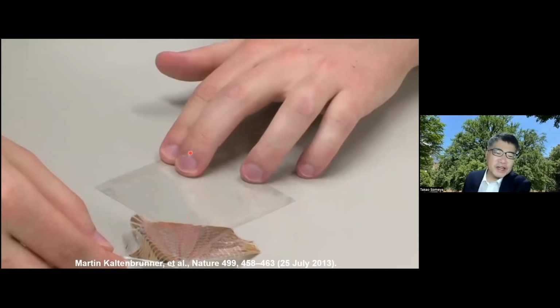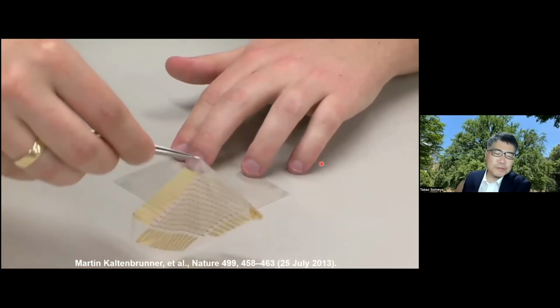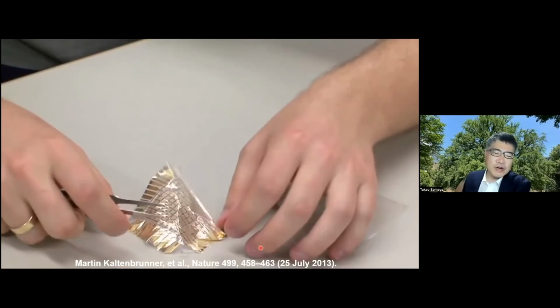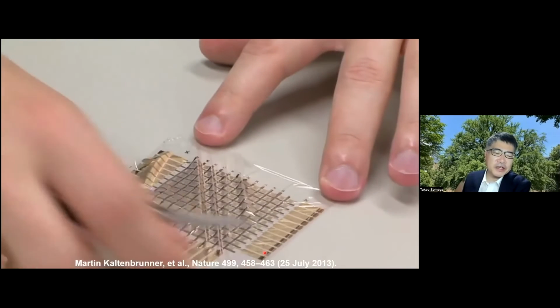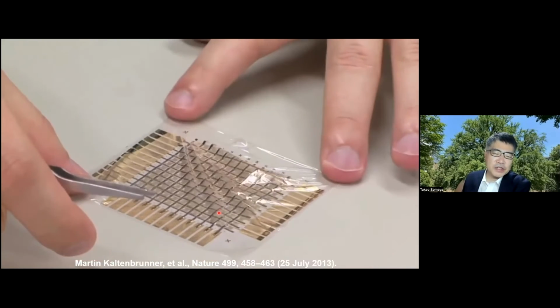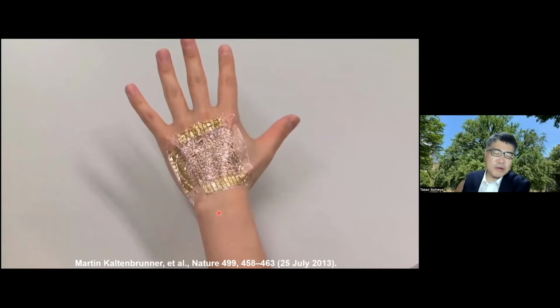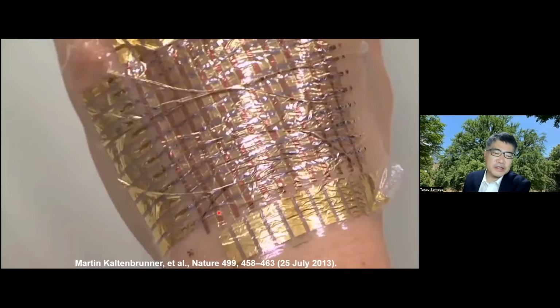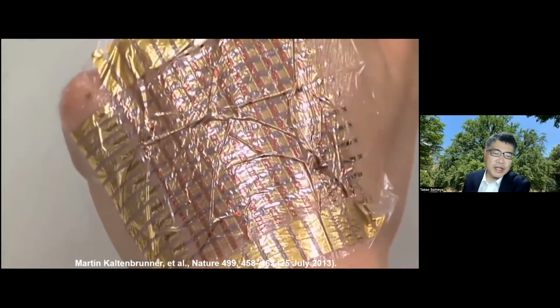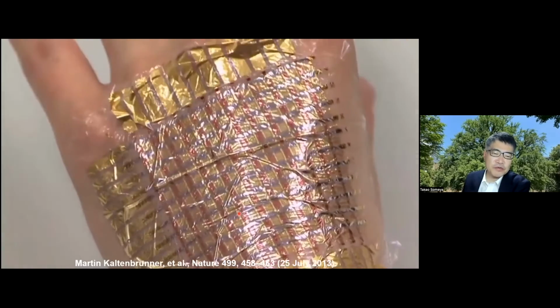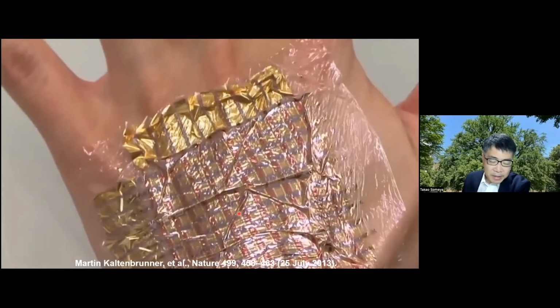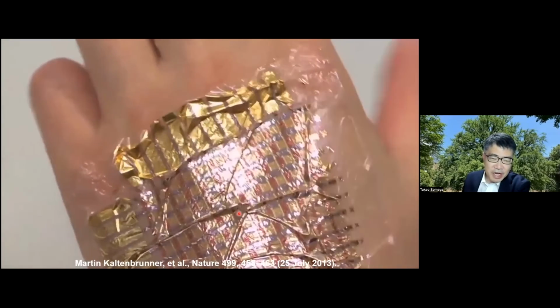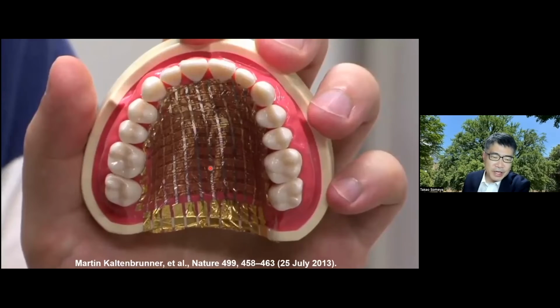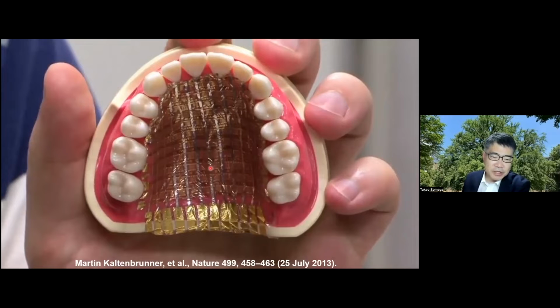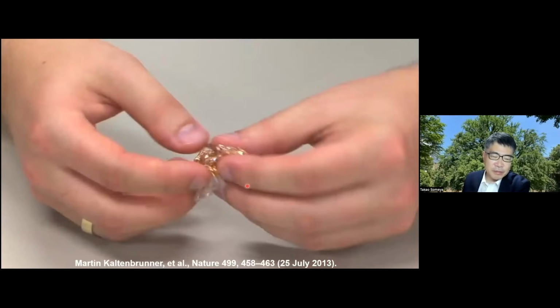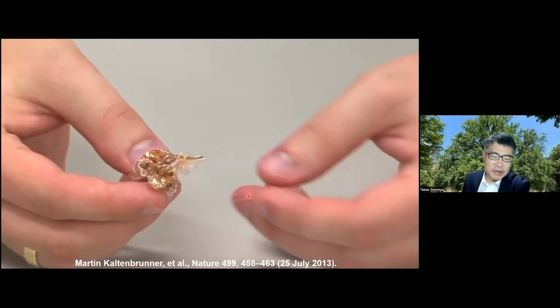when our device reached the ground, it doesn't cause any mechanical failure. Our substrate thickness is as thin as 1 micron, that is a factor of 10 thinner than kitchen wrap. And thanks to the thin film feature, we may achieve amazing conformability and apply it to complicated surfaces, and crumpling doesn't cause any mechanical failure.